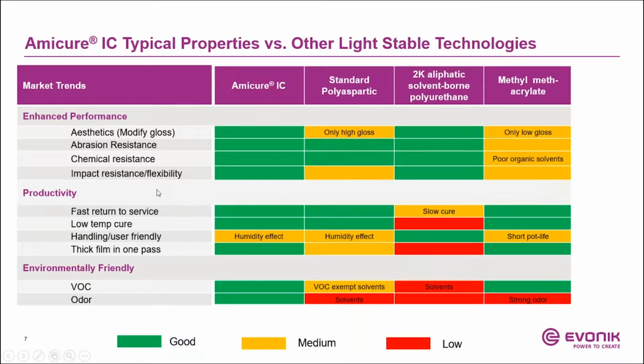Okay, now let's get into the productivity section. And so we'll talk about fast cure and low temperature cure. So you can see the polycarbamide technology, again, similar in terms of chemistry as standard polyaspartic. So they are very fast cure. And also MMA, I would say, has even faster cure at low temperature, fast return to service. Polyurethanes in general do not cure fast. And again, I'm talking about aliphatic polyurethanes, not aromatics. Aromatics tend to be faster, but we talk about light stable systems. So we talk about aliphatics, and they tend to be slower in terms of cure. And generally, they also have a lot of solvent. They do not cure as fast at low temperature.